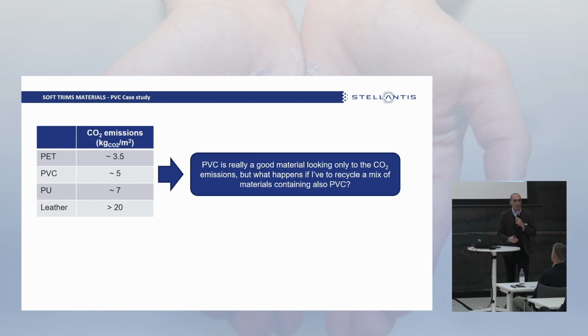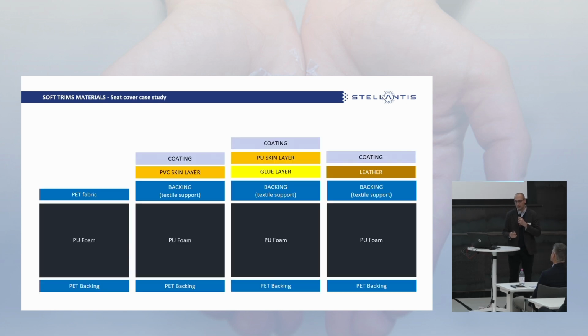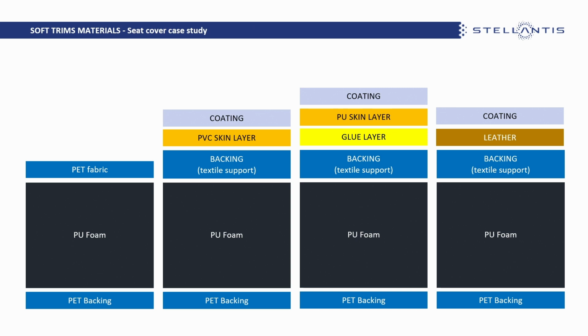main constraint. If I have to recycle the material coming from the vehicle, PVC will be an issue because it's a pollutant for the other polymers, and also because, as I showed you before, the structure is not a monomaterial, not only PVC, but we also have polyester and polyurethane. And we can see this clearly looking also at this other slide that is related to the structure of the material used for the seat covers.